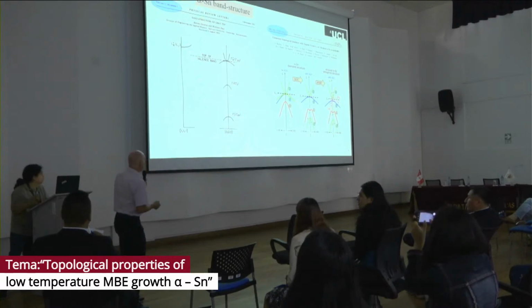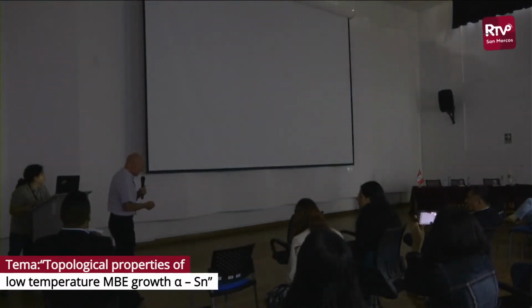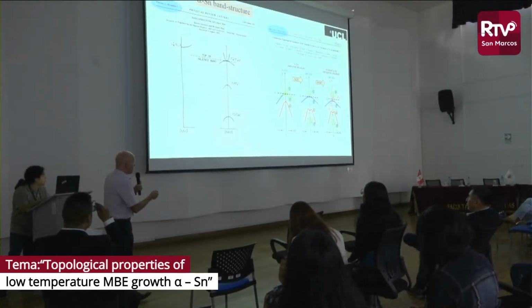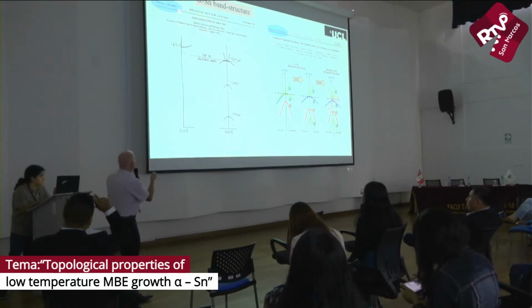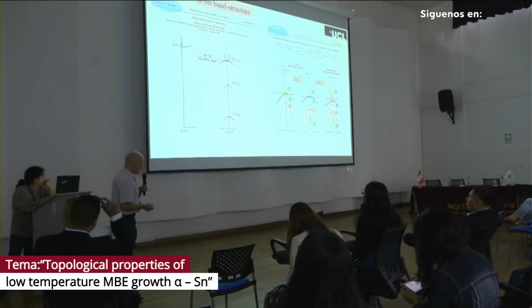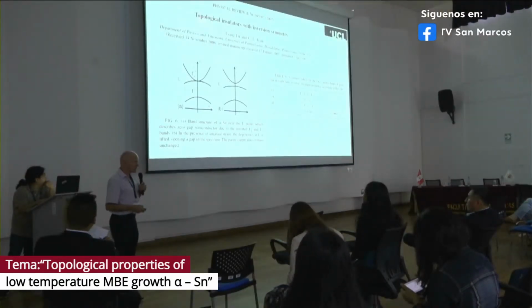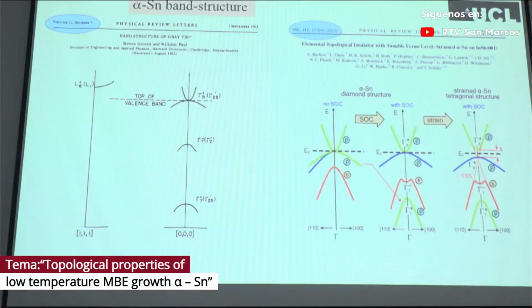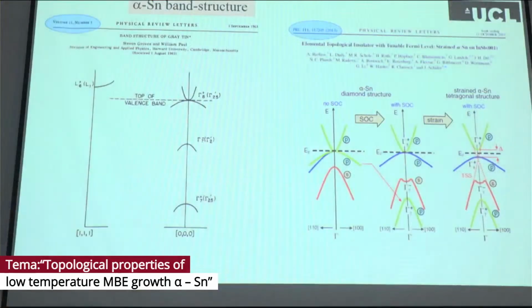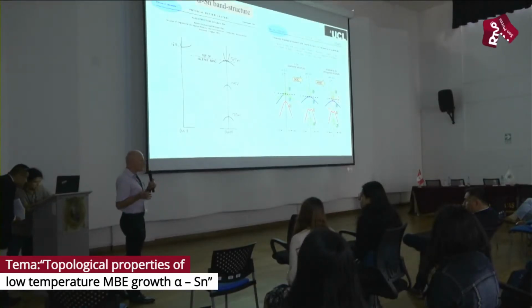Go back a few years in the literature to see where the band structure of tin was first published, and we go back to 1963. It may be earlier. I've just picked one paper from the literature that I know. This paper from Bill Paul's group at Harvard. What he did was a very simple measurement. He, or one of his students, applied hydrostatic pressure to a tin device. The gap opened up. They did some transport measurements, and they published it in PRL. And it was in the days where, if you looked at PRL, you could have a data plot with 5 data points, and that was enough for your PRL.